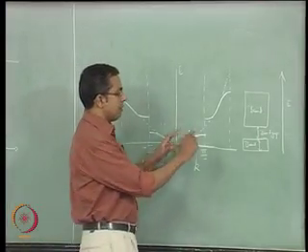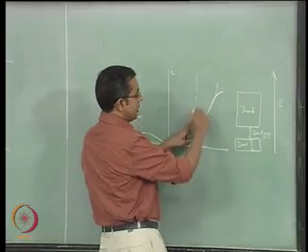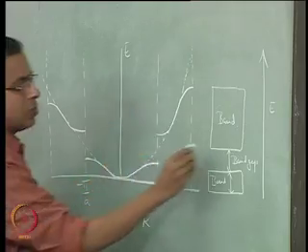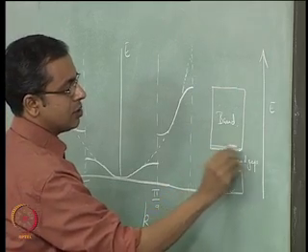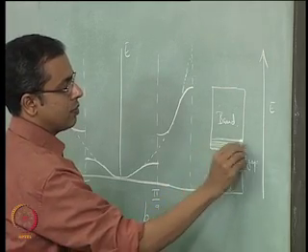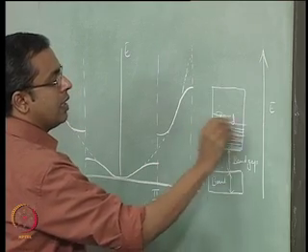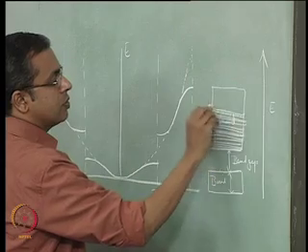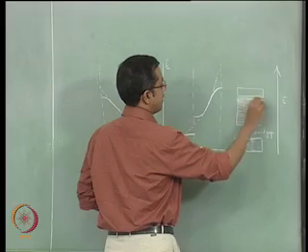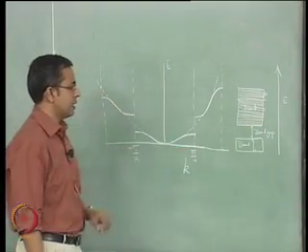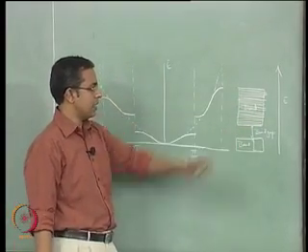I will also highlight one more thing. I mentioned this several times, that this looks like a continuous curve, but it is several discrete points, and so this simply means that this band is a series of discrete energy levels that are allowed. They are very closely spaced relative to the band gap values, or even the extent of the band. So please always keep that in mind. This is a series of discrete energy levels which are extremely closely spaced, and then you have the band gaps.